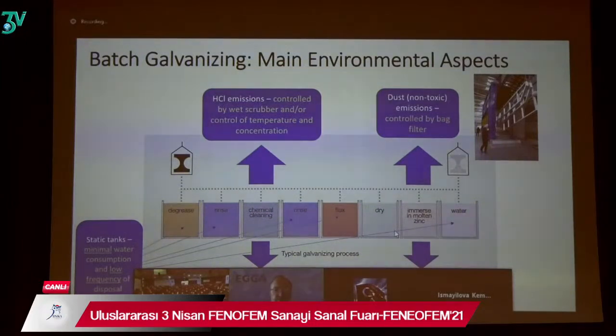From the galvanizing bath itself, the immersion in molten zinc, we have a particulate emission, so a non-hazardous, non-toxic emission of small particulate, usually containing mostly ammonium chloride, and that is controlled by bag filters normally. In the past, sometimes wet scrubbers, but bag filters are extremely efficient in cleaning the captured emissions.